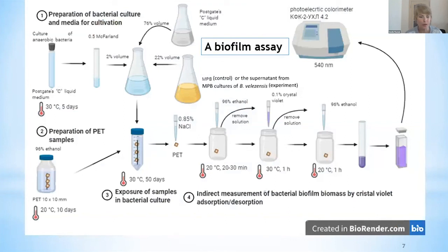To study the intensity of biofilm formation on the PET surface, 10 by 10 millimeter samples of PET were cultured in Postgate C liquid medium, 76% of the volume, with the addition of supernatant from meat-peptone broth cultures of Bacillus velezensis NUCC1 or NUCC2b, obtained after centrifugation for 10 minutes at 5,000 rounds per minute, 22% of the volume, and a culture of Desulfovibrio oryza NUCC-SRB1, 2% of the volume, during 50 days. For the biofilm assay, indirect measurement of bacterial biofilm biomass by crystal violet adsorption-desorption was used. Statistical analysis of the obtained results was performed using the statistical model of Microsoft Office Excel 2010.